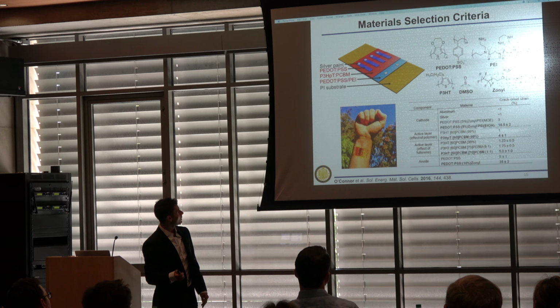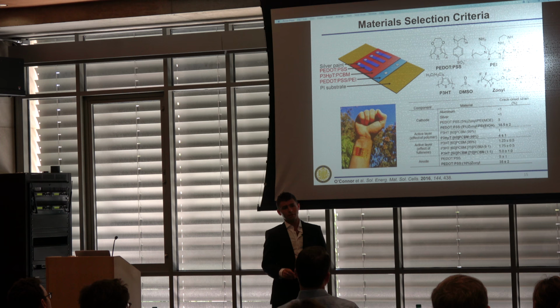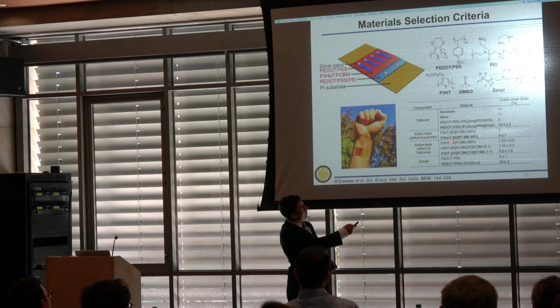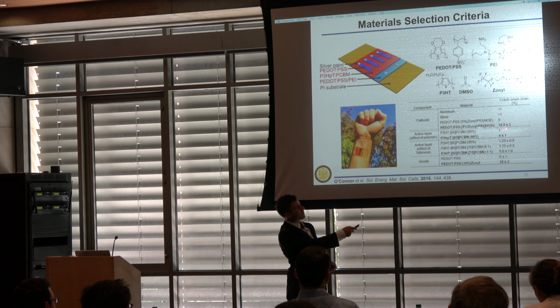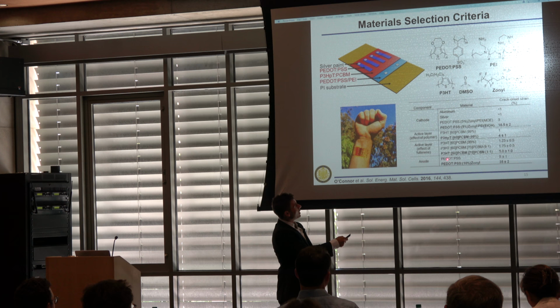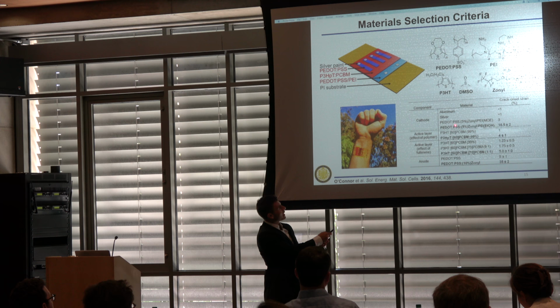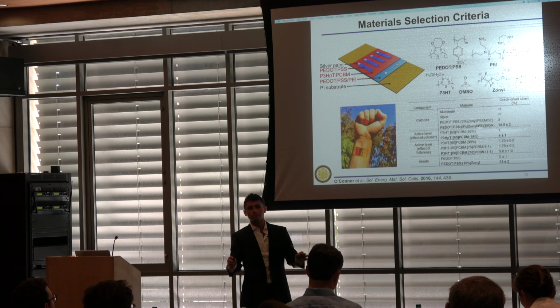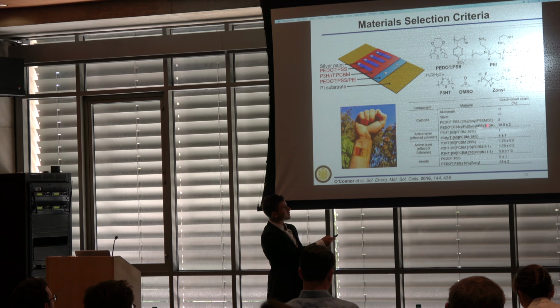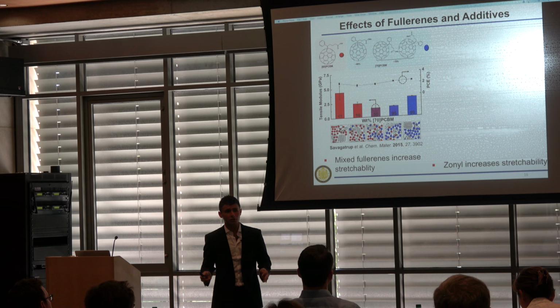And we actually went to the effort of optimizing every layer for its electronic performance and its mechanical resilience. So you see C70-PCBM, compared to C60-PCBM would crack at 1%. We now can withstand and accommodate 4% strain. By choosing our fullerenes properly, we can get another 1%, so 5% strain out of this. Now, PEDOT, if you process it incorrectly with PEI, cracks at only 3%, so this would then be the weakest material, and it would shatter as well. So we plasticized the material and changed the solvent in which we processed the work function treatment. And this was also informed by the material studies of our lab.